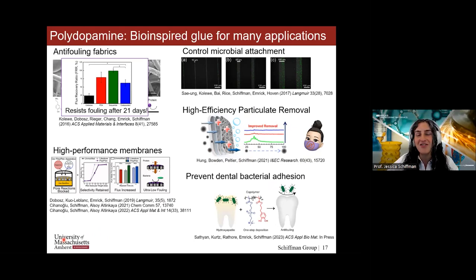And then finally, we're waiting for the proofs on this paper right now. This is also a little bit different. We actually showed, okay, we don't have to use dopamine and a polymer. We can actually work with some very good collaborators, again the Emrick Group, at making a copolymer where we can balance a sticky and a slippery group on the same backbone. In this case, we showed that we can actually have self-adhesion of these copolymers onto hydroxyapatite, which is a tooth mimic. And then we did a really cool assay, which was like using mouthwash, and all the bacteria fell off of our teeth.